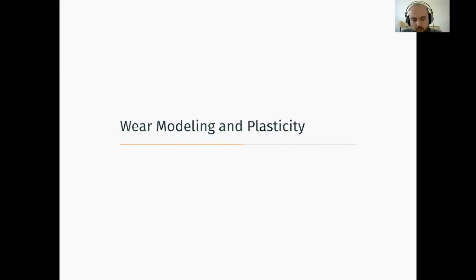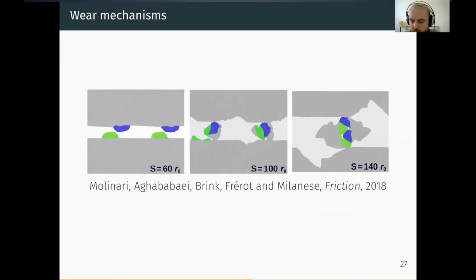So I've showed you a way to do elastoplastic rough contact, and I'm going to try now to apply it to a practical problem of wear modeling and the influence of plasticity on crack nucleation. So let's discuss a bit wear modeling. There have been some studies in the past 5 years, particularly in Jean-François Molinari's group, on microscale or nanoscale mechanisms of adhesive wear. If you're not familiar with this, or if you missed Jean-François's seminar a few months ago, just to recap a bit, there's a critical length scale to nanoscale wear. Basically, if you have two asperities that collide, and the contact is smaller than a critical length scale, you have plastic deformation, and you have no detachment of debris particles. So essentially, you have no wear.